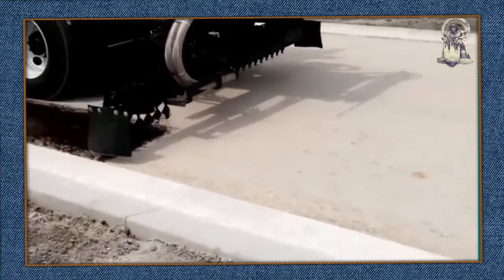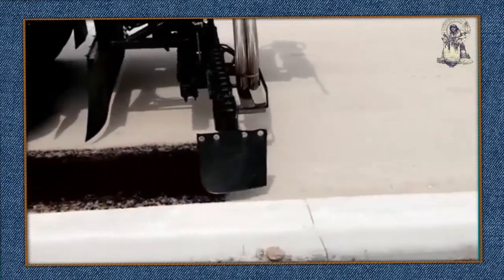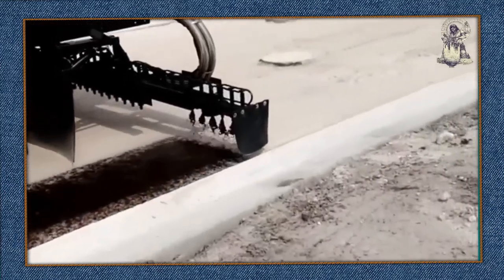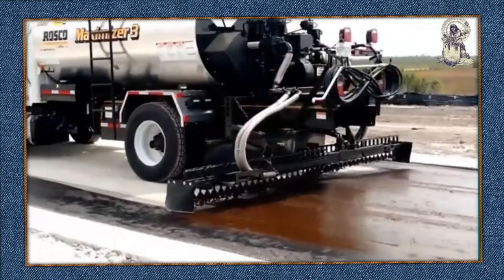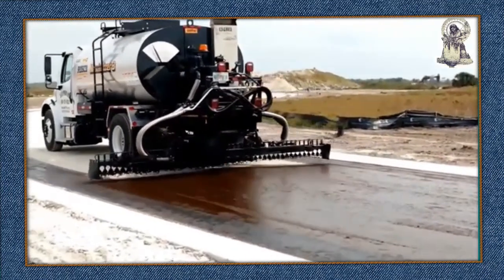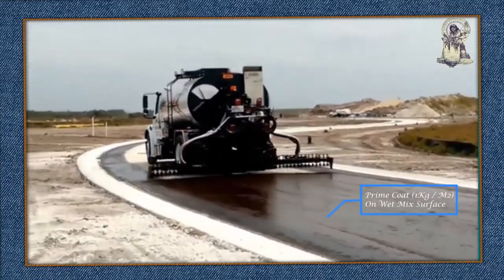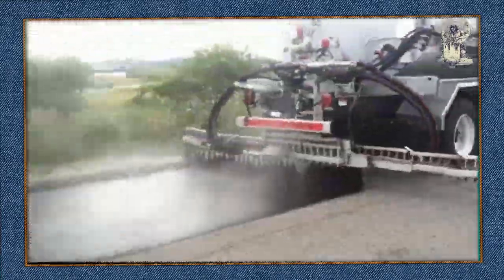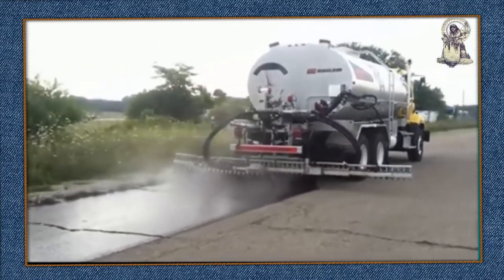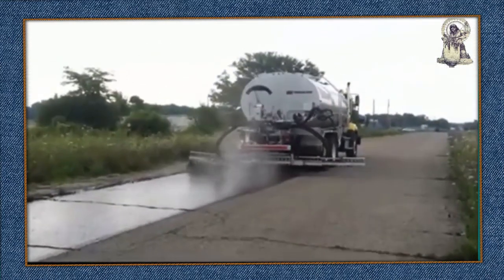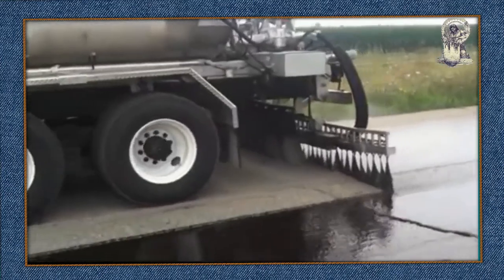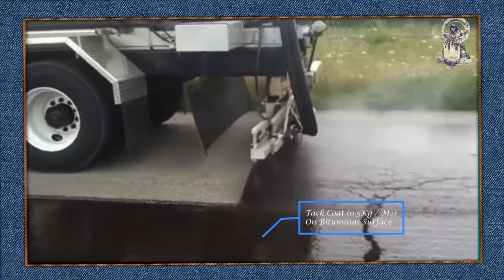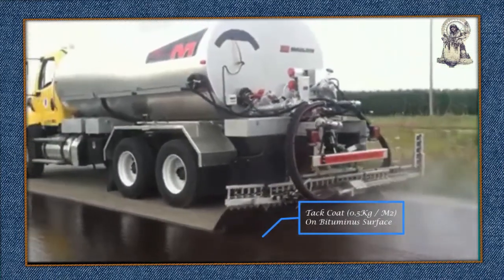The prime coat is the binding layer between bituminous and non-bituminous surfaces, such as wet mix macadam. Around 1 kg per square meter of cutback bitumen 70 is sprayed as prime coat. And normally, it is allowed 24 hours to penetrate into the wet mix. It is uniformly sprayed over the surface with the help of mechanical equipment. And tack coat is the binding layer between two bituminous surfaces. Around 0.5 kg per square meter of bitumen is used as tack coat. And it is uniformly sprayed over the bituminous surface just before laying the next layer with the help of mechanical sprayers.